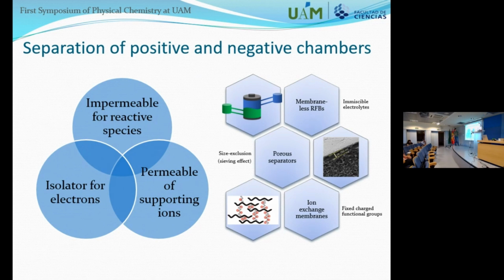And what we have in this case is that we have fixed charges with the functional groups that are linked, they are fixed in the membrane structure. Usually, also when we have ion exchange membranes, of course, we have some channels in the structure. So more or less always we have a mixture of ion exchange membrane with some sieving effect separation. So we cannot disconnect these both things, but the pore separators are only based in this size exclusion effect, while the ion exchange membranes have the fixed charges. Well, these are the ones that we're going to focus on.